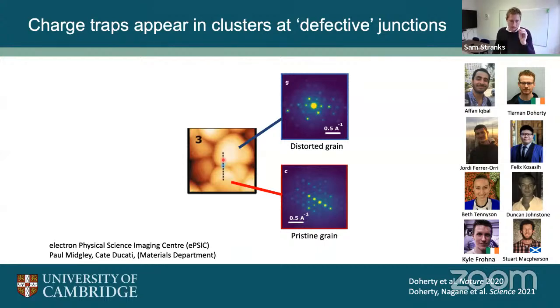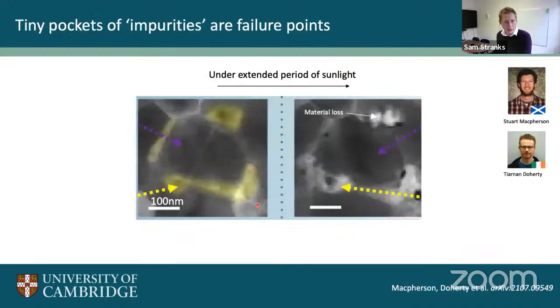And so this is really interesting. It tells us it's really these little tiny locations which will be important. And these are important not just for carrier trapping, but also for degradation of the material. As we operate the solar cell over time under sunlight, for example for many years, these tiny little sites that trap charges are also sites where we start to lose our material.